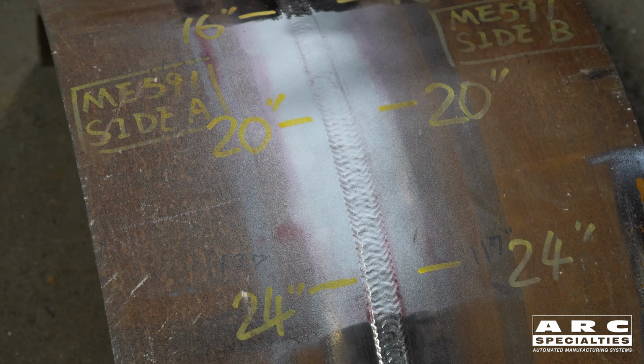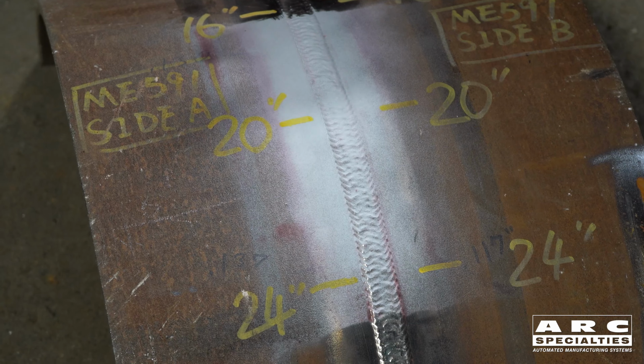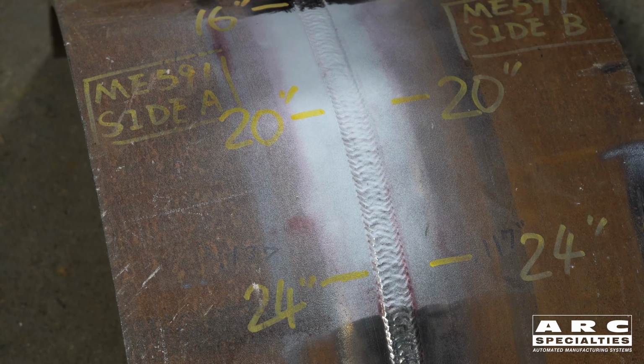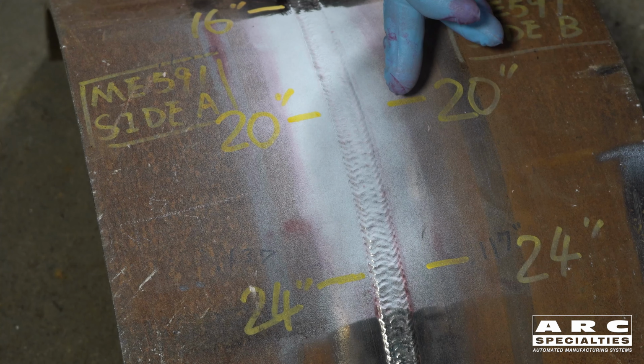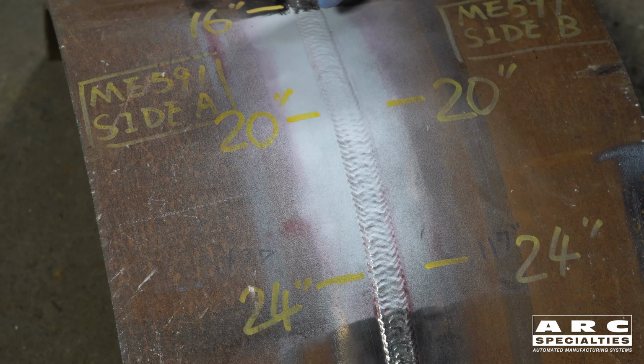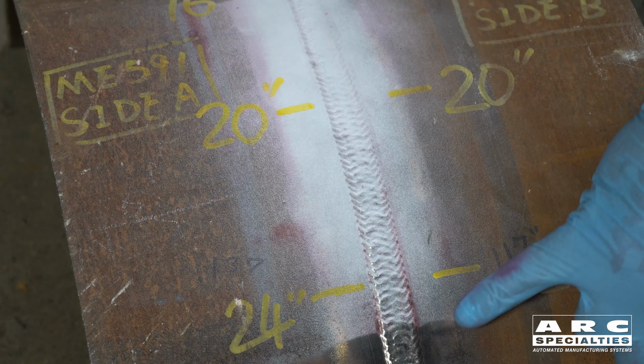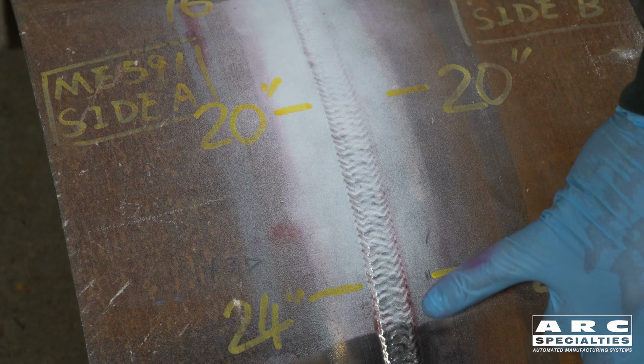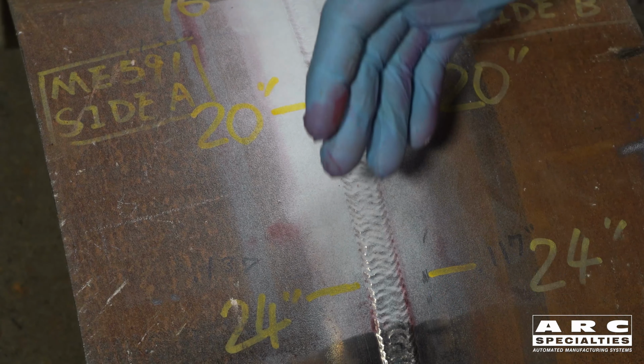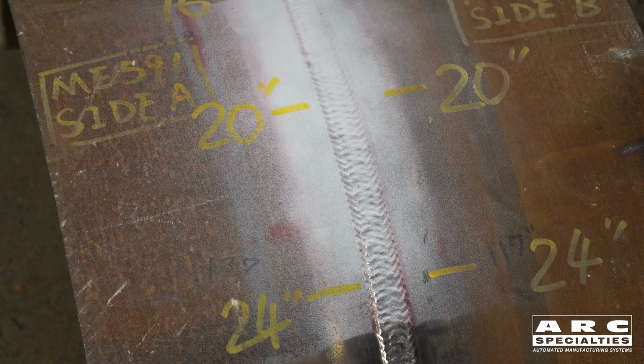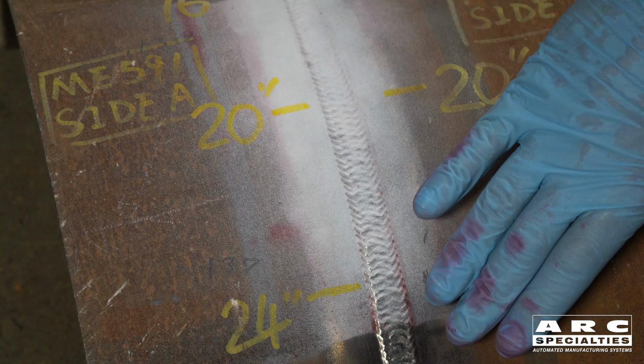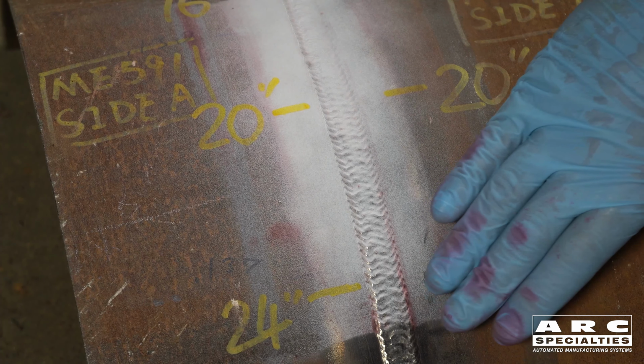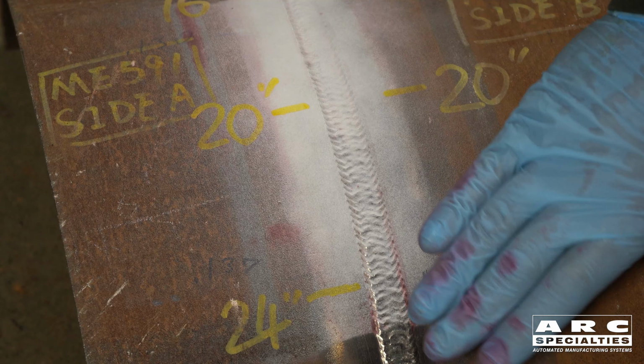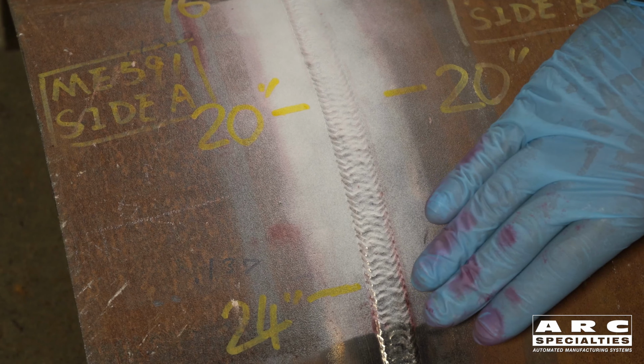All right, now we've waited 10 minutes, our minimum for the dwell for the developer, before we make any calls on any indications that so happen to come up in this weld. This area here, we got a little bit of a red hue. That's probably maybe just a little bit of poor cleaning on my part, but I would still go further with the inspection due to, I have no serious red bleed out, just a little bit of a pink hue.